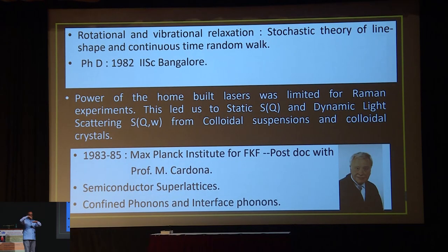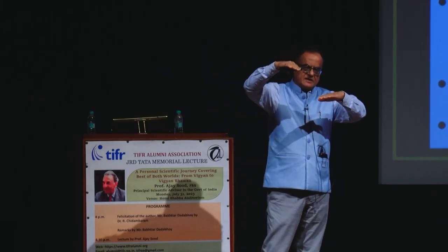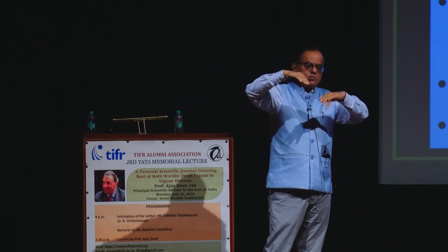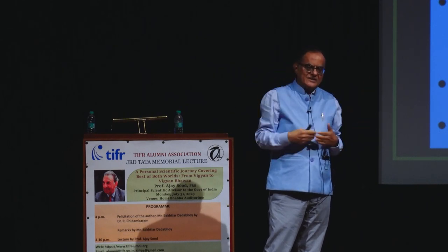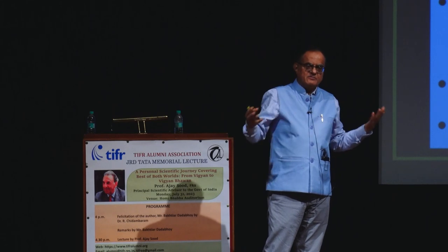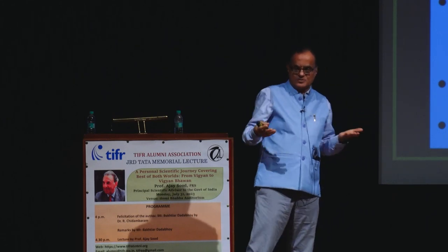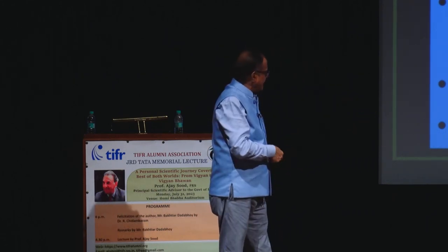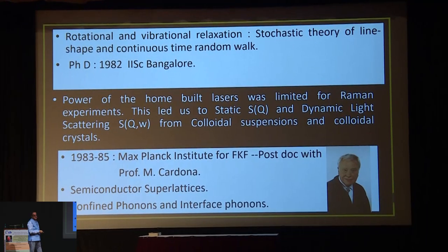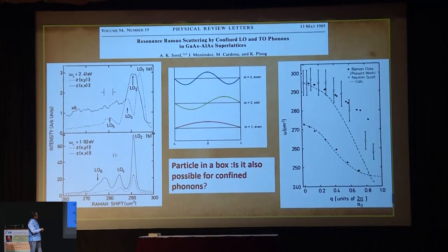These are alternate layers of two semiconductors. Each layer is only about 20 angstrom. So this is nanoscience in the very beginning, but it was not called nanoscience at that time. And that gave rise to very interesting physics, of which I will give you an example.